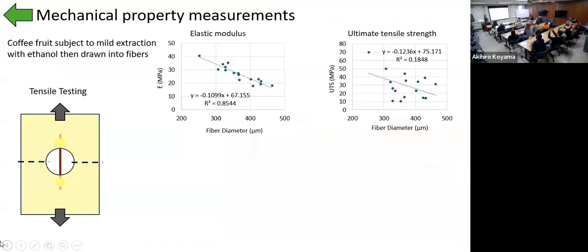And I even was able to run mechanical testing on just this mild ethanol treatment. And what you see here, if these numbers mean anything to you, is that I got an average of about 25 megapascals of strength, which is actually starting to get into a usable level of strength for a material. But this is my dissertation work, so it kind of ended where it ended, as you'll find out when you get to the end of your PhD.